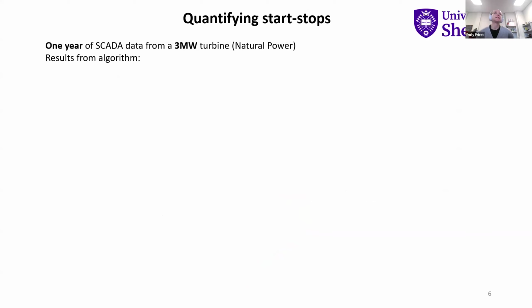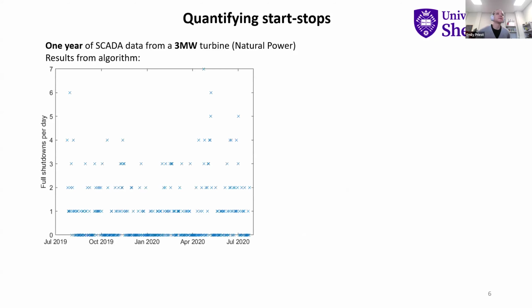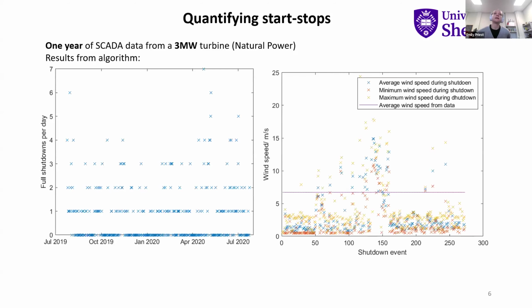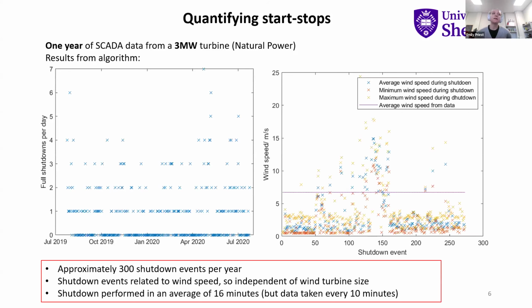So I studied 1 year of SCADA data from a 3 megawatt wind turbine, and I got some results in the algorithms. You can see the shutdown events over the year, and you can see me correlating the shutdown events to the wind speed. I found approximately 300 shutdown events over the year, and I related them to the wind speed, so we can say that these are independent of our wind turbine size. I also recorded the length of the shutdowns, which are about 16 minutes, but our data is only taken every 10 minutes, so we have to take that with a pinch of salt.